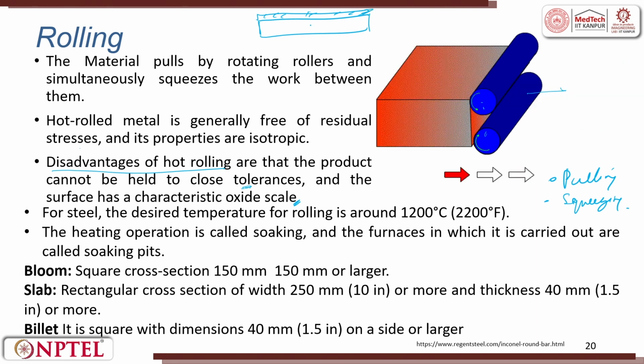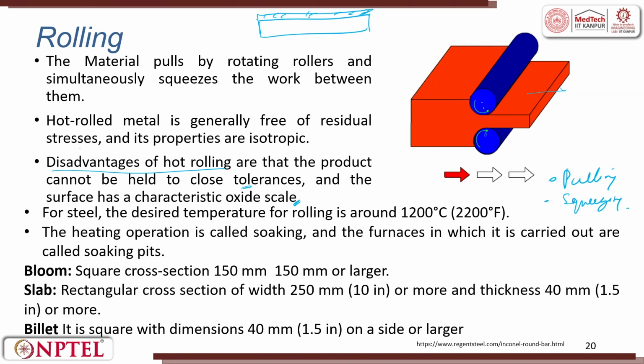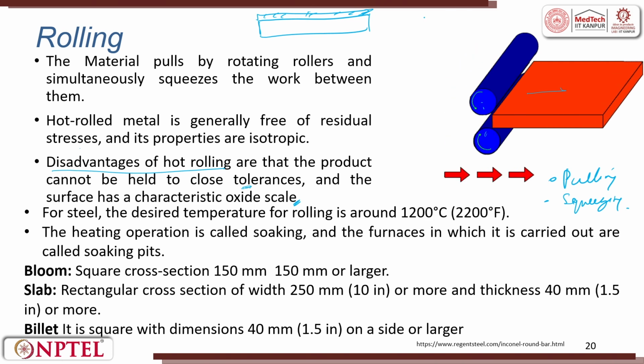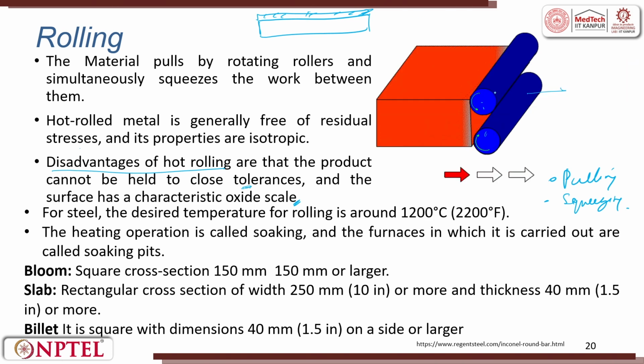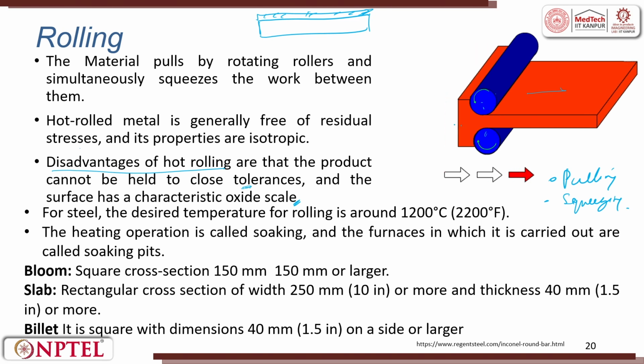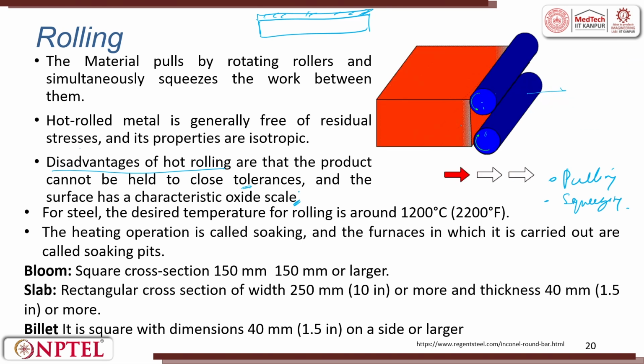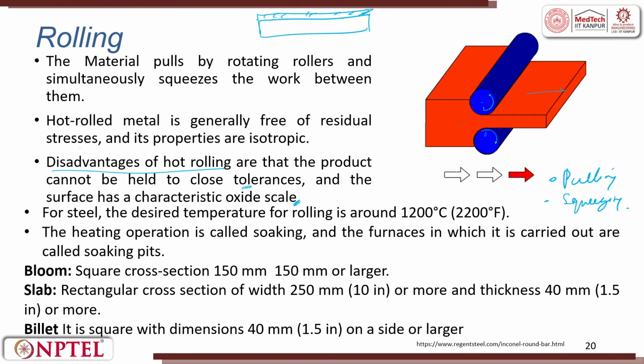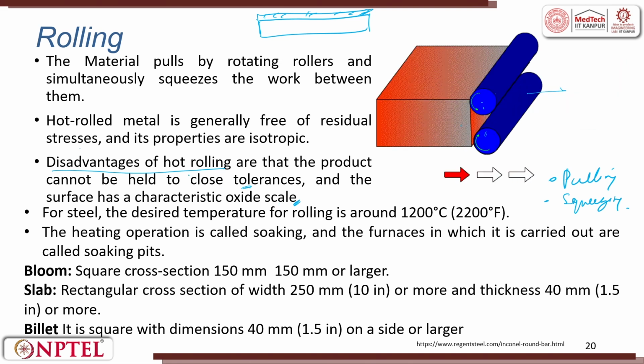The next time when you try to roll this, the oxide will easily crack, and this can scratch the roller as well as the workpiece. So, oxidation scales should be avoided, which becomes very common when we start working on hot rolling.